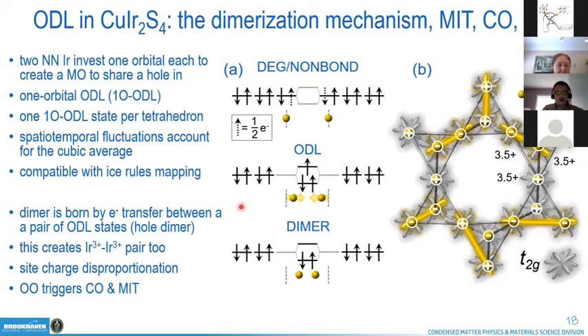Now, as far as dimerization and the metal insulator transition go, spin singlet dimers are born out of transfer of charge from pairs of ODL states. In that context, it's a hole dimer. If we have two ODL states like so, and one of those electrons jumps onto the other ODL state, then what remains is a dimer. On the other hand, the other ODL state that receives an electron will become d6, and in that sense, ODL inactive.